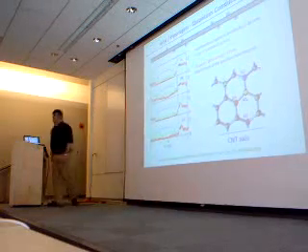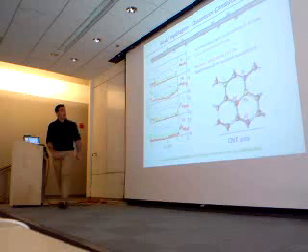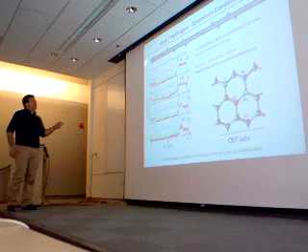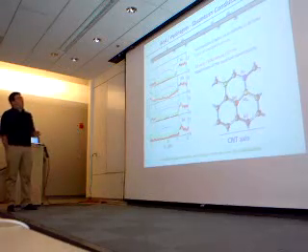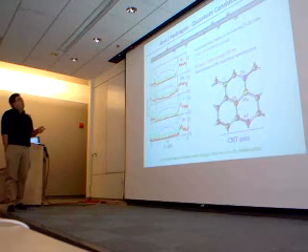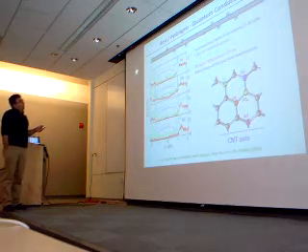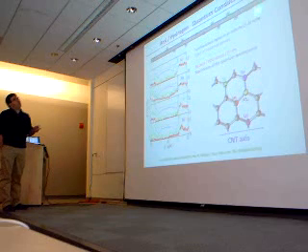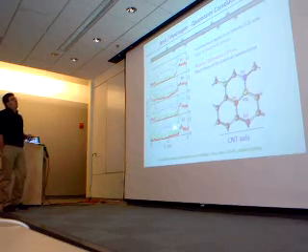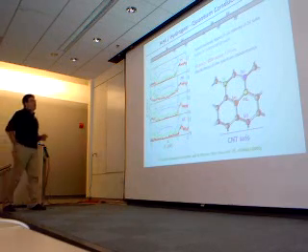And just to conclude, to go back to our transport properties, we were able to calculate transport properties in this system, and actually discovered that the probability of an electron to go through this functionalized region was decaying very, very rapidly with the number of molecules.